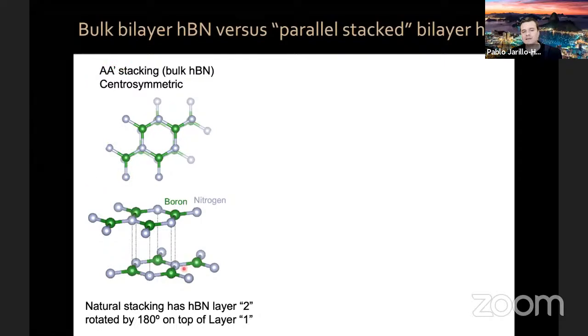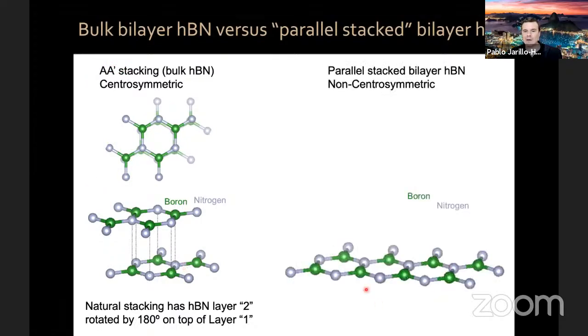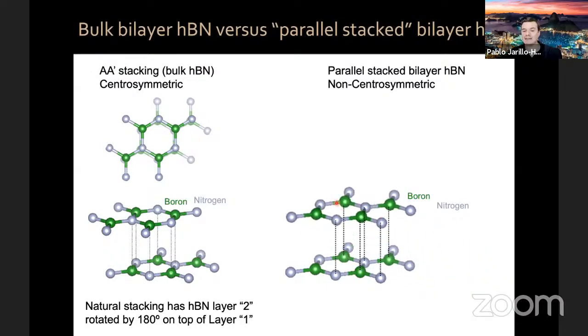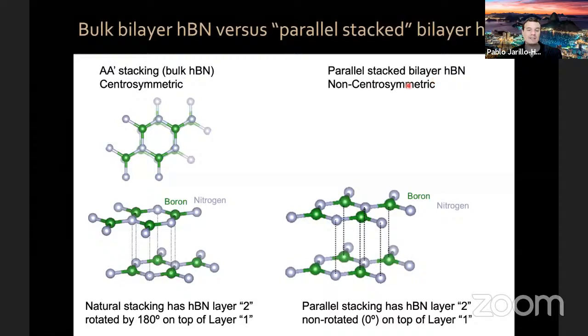Now, one layer of boron nitride, however, is non-centrosymmetric. So if you take one layer, and now I'm going to draw these lines here so that you can keep track of these atom positions, and if you now make a copy of this one layer and stack it parallel on top of itself, you can see now a boron atom has on top a boron atom. A nitrogen atom has on top a nitrogen atom. Nitrogen, nitrogen, boron, boron. So parallel stacking has the hexagonal boron nitride layer number two, non-rotated, 0 degrees, on top of layer one. For the natural stacking, layer number two is rotated 180 degrees with respect to layer number one. This means that parallel stack bilayer HBN is non-centrosymmetric.